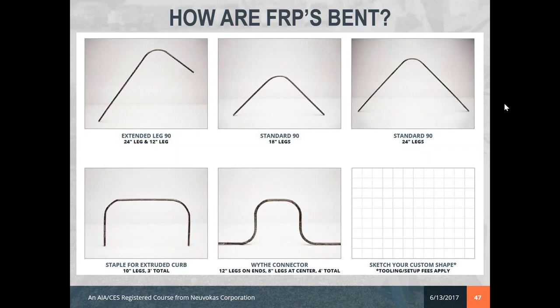Everybody wants to know if you can bend FRPs. Just like with steel, you'd have to send them to fabricators ahead of time to get bends done. You need to bend any sharp angles with FRPs prior to the epoxy setting, but they can be done, and these are some general shapes that are used in the industry. You can take a piece about 20 foot long and generally be able to bend, especially basalt FRPs, to about a 2 to 3, 4 foot radius. It depends on the size of the bar, but you can make a radius out in the field as opposed to an abrupt bend. But they can be used, they are used, and are available.